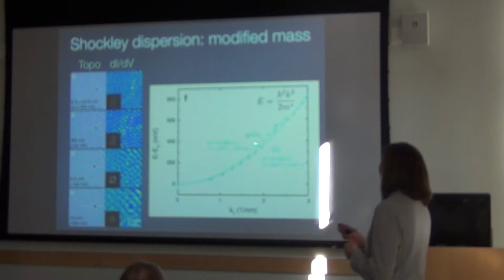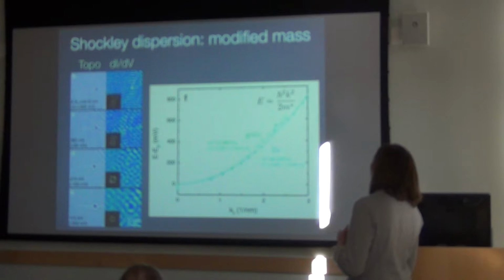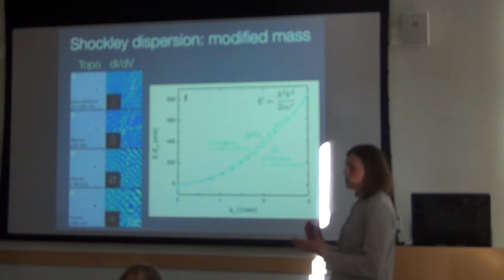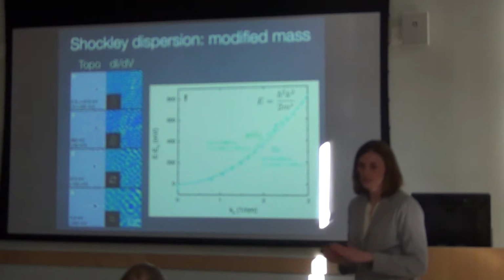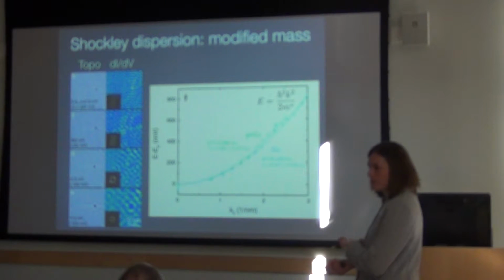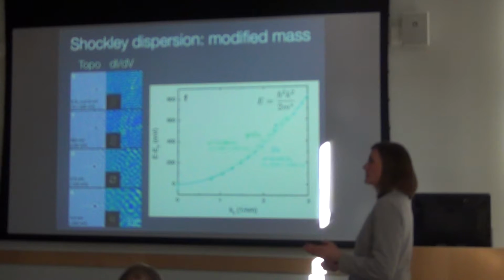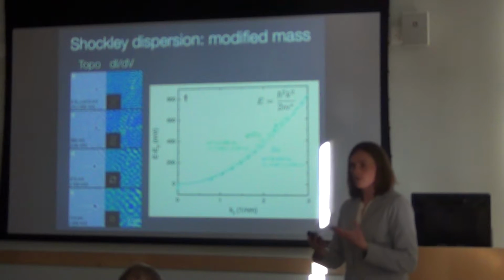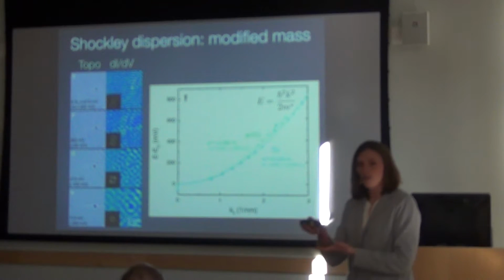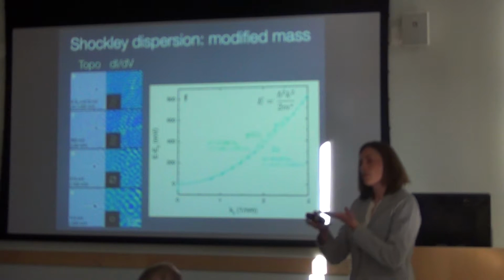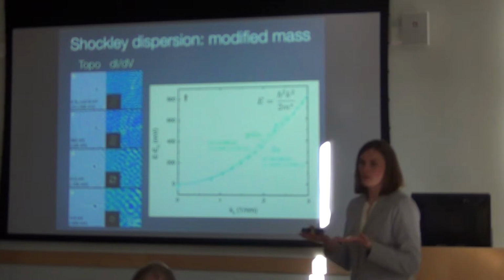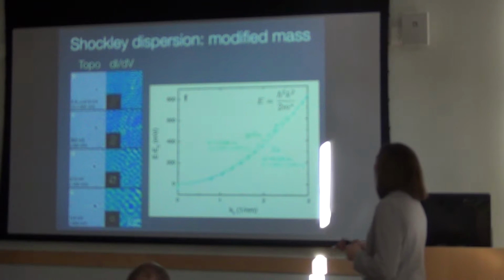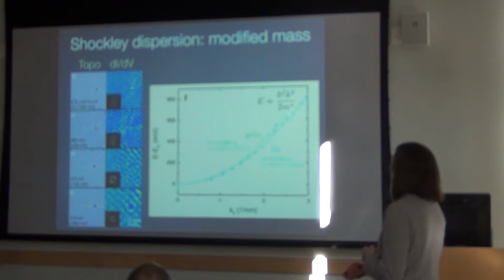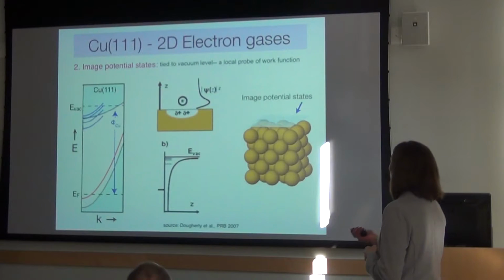So it's actually a lower, the electrons behave like they have a lower mass over the graphene regions than they do on the bare copper regions. So one way to think about this is that maybe the potential that the electrons see on the surface of the crystal has been sort of flattened out by the presence of the graphene. That was kind of a fun thing to do.